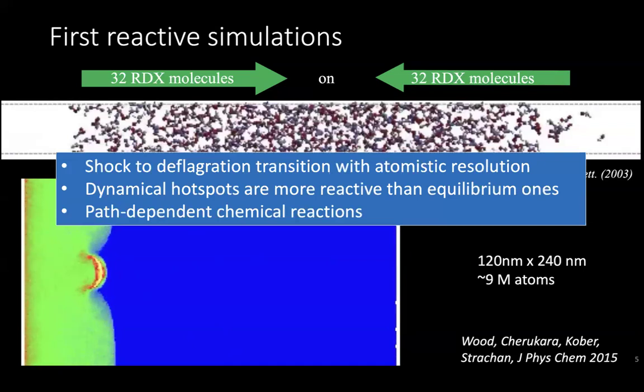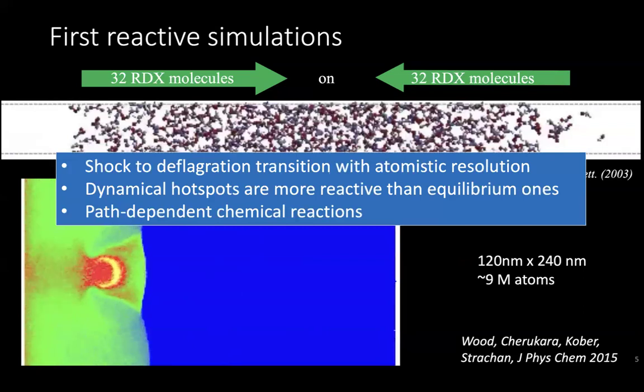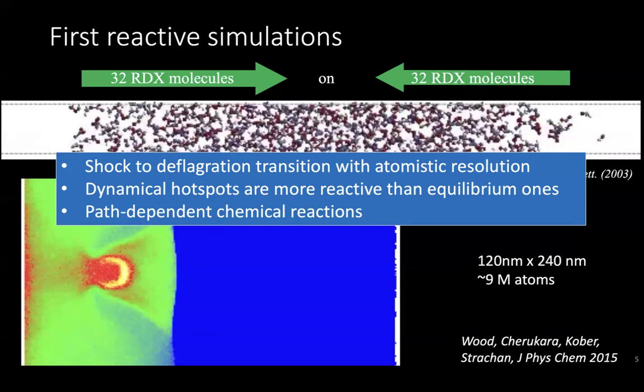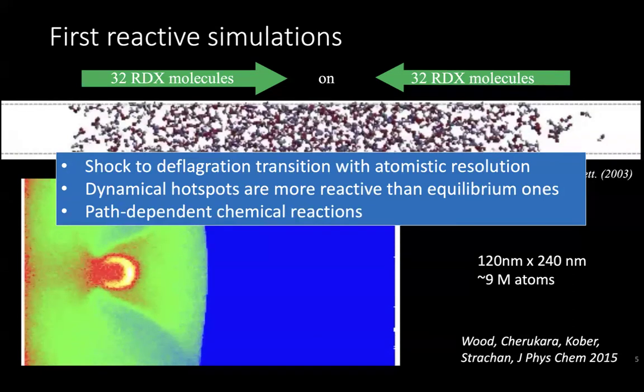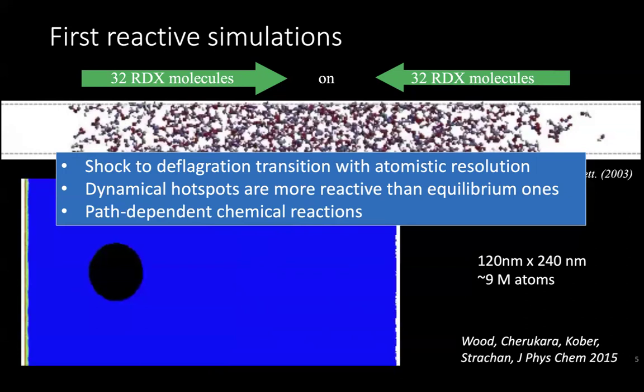Just like the first ever, these simulations early on, what we found is that this hotspot that was generated dynamically by a shock wave was way more reactive than what we could anticipate based on its temperature and its pressure. So if I take a system and I compress it and I heat it up to the same temperature, it doesn't react nearly as fast. So this is path-dependent chemistry. It's not just the thermodynamic state, it's how you got there. This was a very puzzling result.